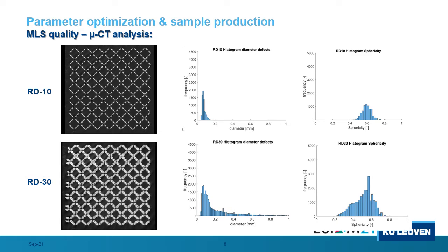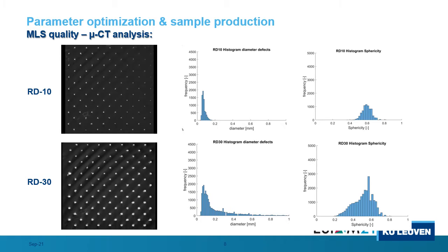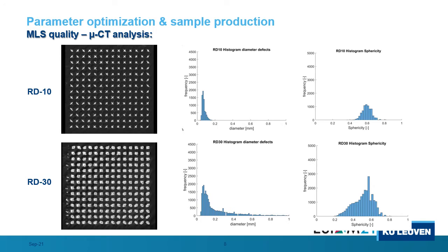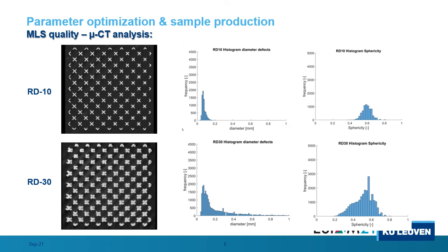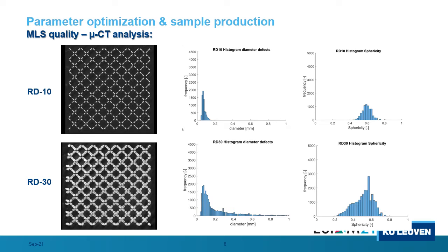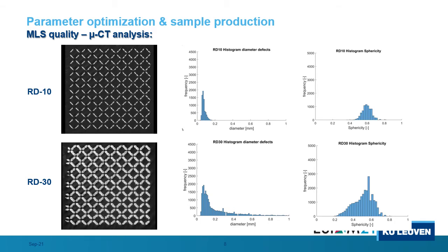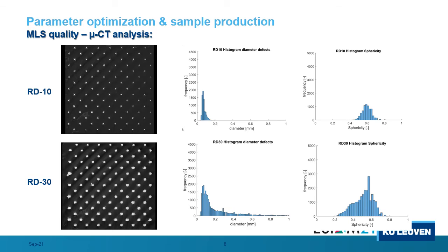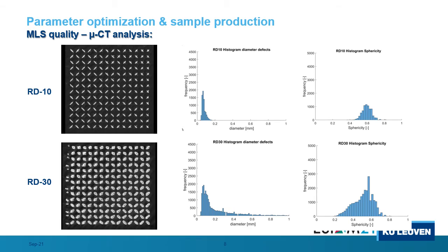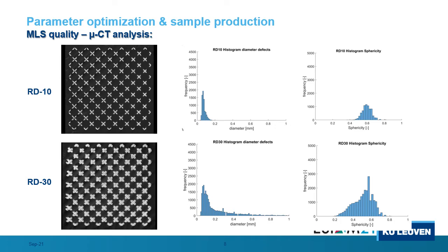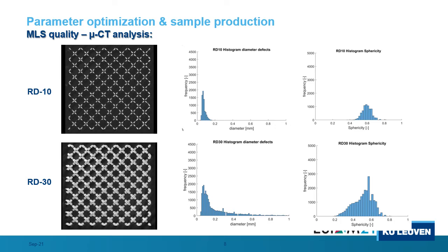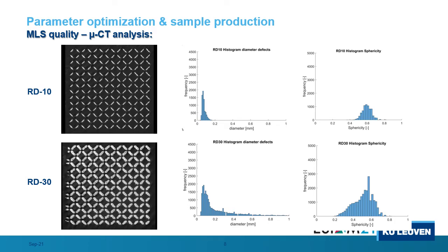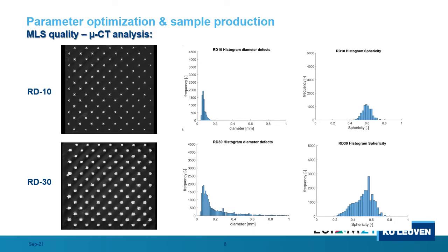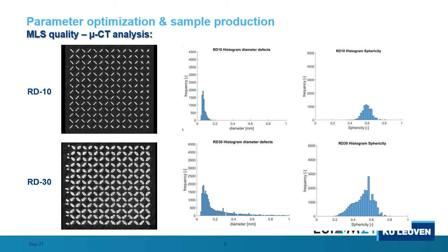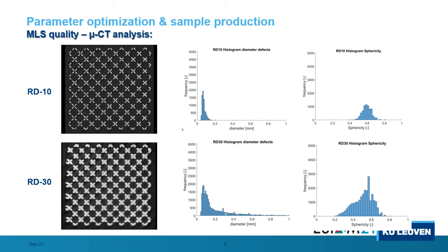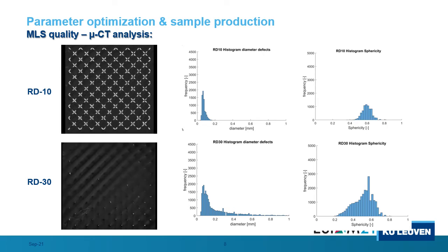For RD30 coupons, there are clearly larger internal defects, both at the node locations and along the struts. These defects have low sphericity, meaning that they can be classified as lack of fusion pores. The presence of these defects can be explained considering the scanning strategies adopted for RD10 and RD30 coupons. For RD10 the scanning strategy consists only of one contour track. For RD30, the scanning strategy consists of a contour track followed by short infill tracks. These infill tracks are too short to result in a fully developed melt pool with the current parameter set, and so defects are generated.